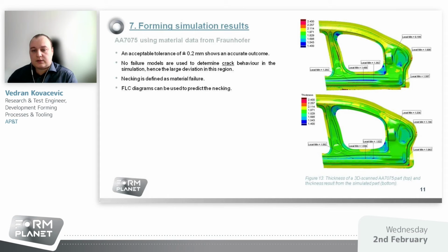Coming to the results for 7000, I can mention that we used the material model Barlat 2000 for all simulations, and looking at the result for the 7000, comparing it with the 3D scanned formed part, it shows a quite accurate outcome. There's a deviation of plus minus 0.2 millimeter, which is acceptable.